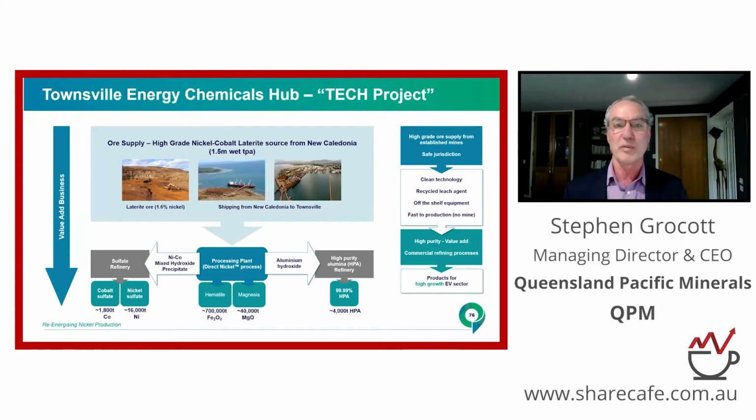Nitric acid's a great solvent for dirt, dissolves everything except the silicates, which are a nice inert residue that you can deal with. It dissolves everything else, including, of course, the nickel and cobalt. We'll process them through into a mixed hydroxide precipitate, which is saleable in its own right. It currently sells for about 90% of LME. If you don't know that, you should subscribe to Benchmark so you can get the data. We'll refine that on site using conventional nickel and cobalt refining processes directly into the high purity nickel and cobalt sulfate direct into the battery industry.